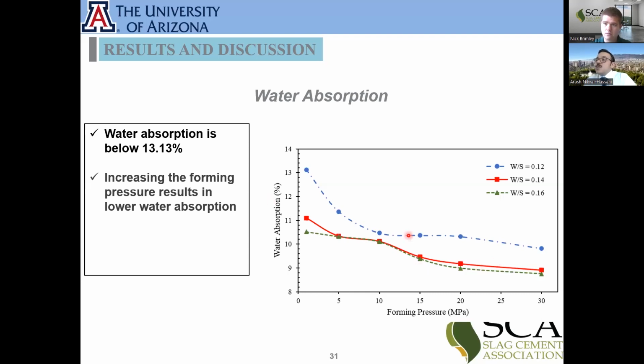And what about the water content? We see that at lower water content, the materials are more prone to water absorption because the water is low. So there is a potential for the extra water to go inside the microstructure and try to saturate the sample. And that's why the water absorption is higher. So the more water we have in the sample by itself, the less water absorption we will have.